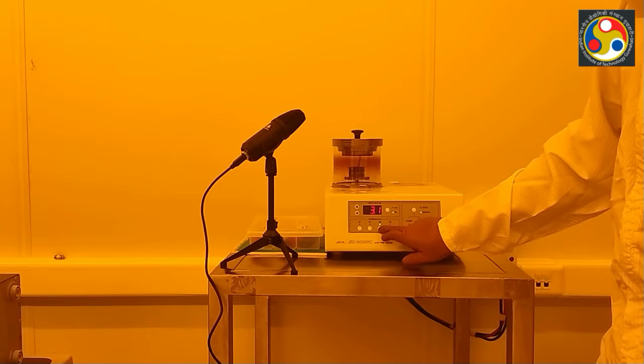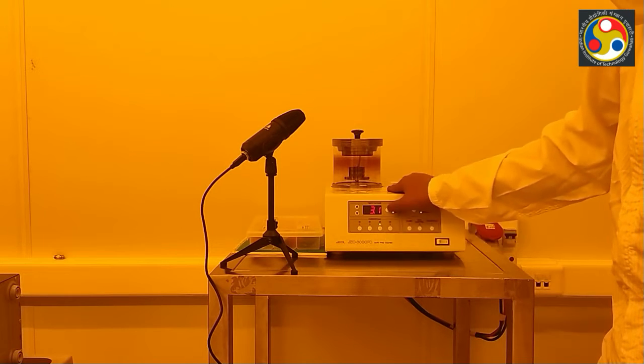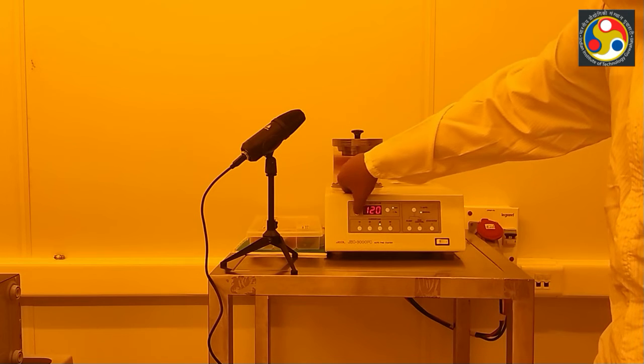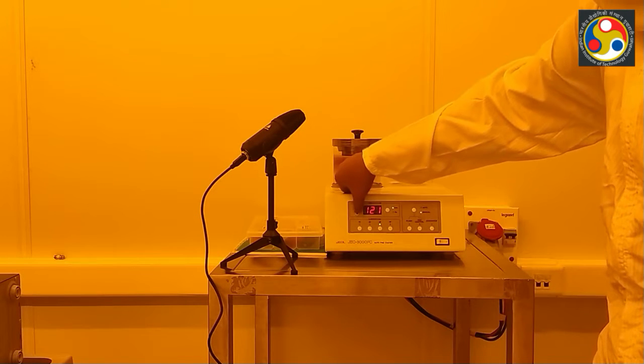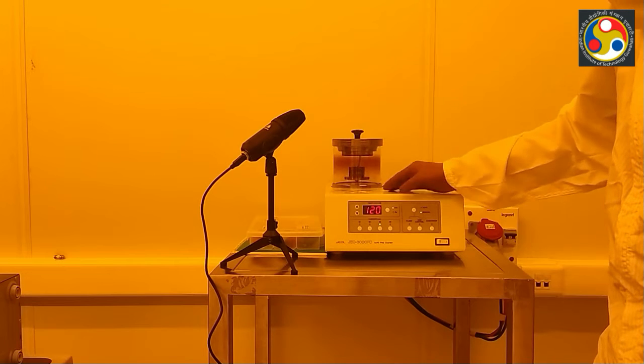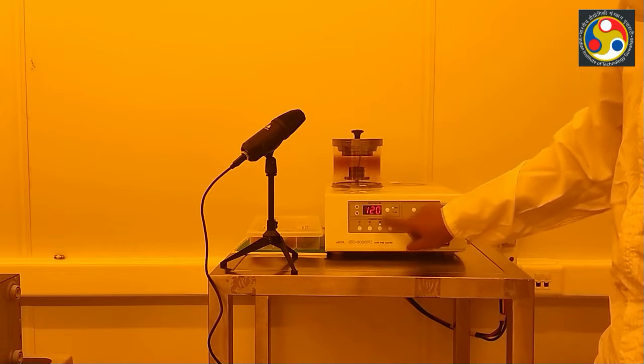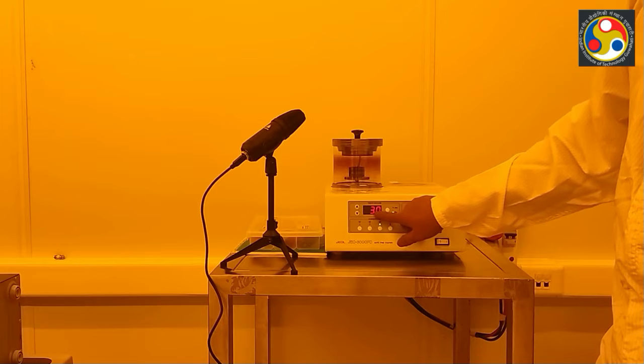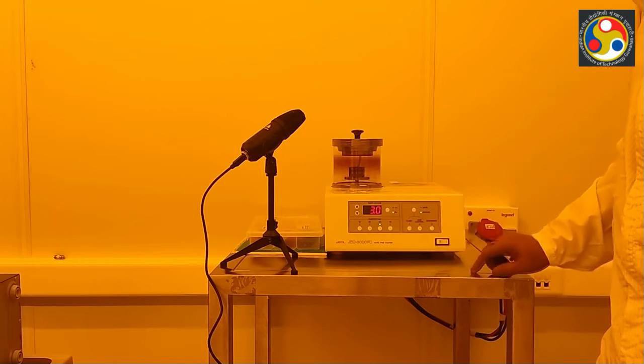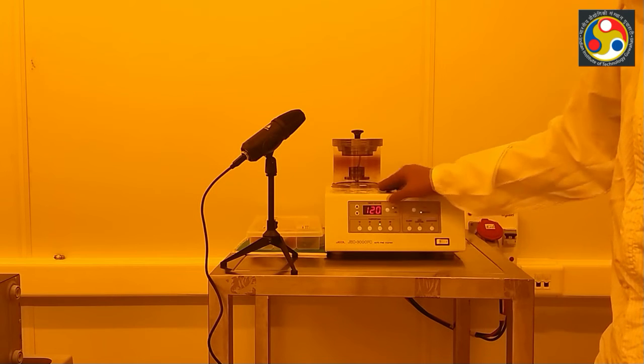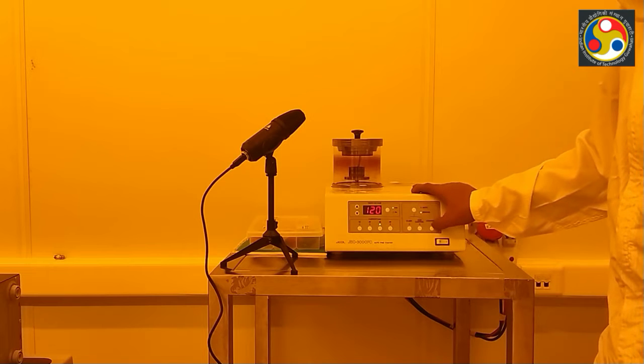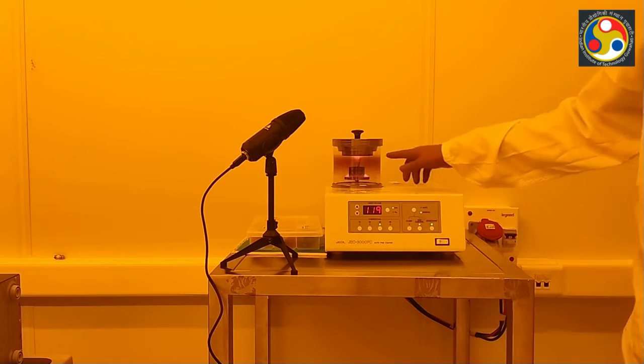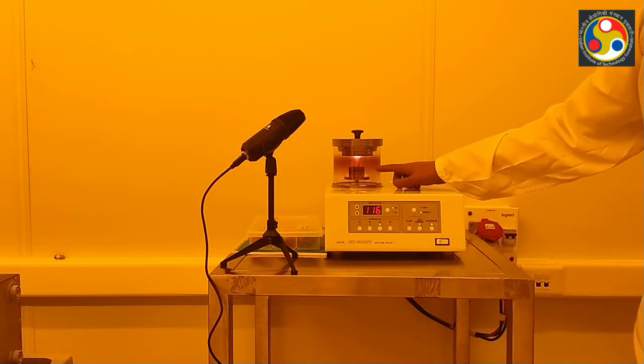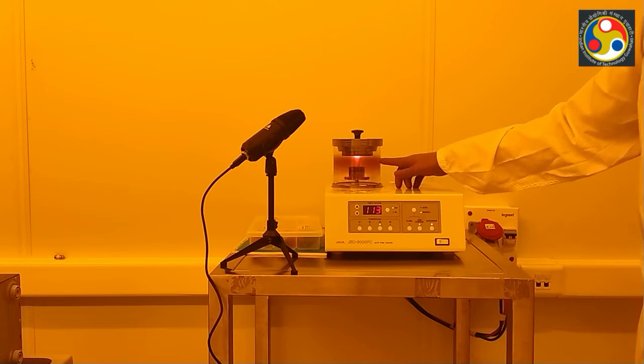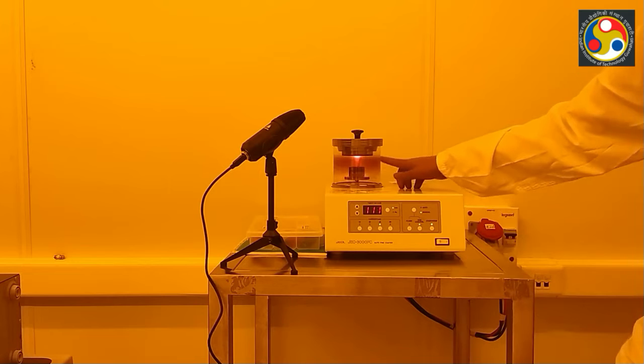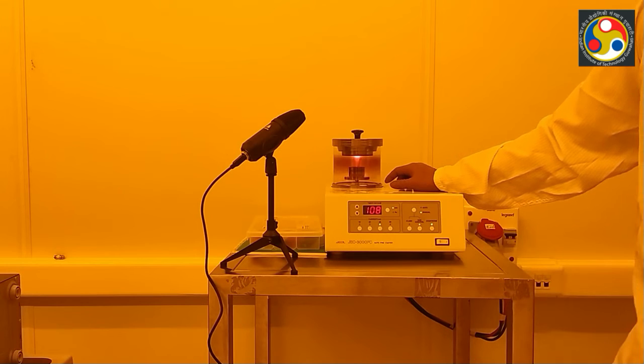The current I am going to use is 30 milliampere and the time I am using is 120 seconds. I can change this time value. I am keeping it 120 seconds and 30 milliampere current. And now the pressure is 3 Pascal, so I can start the system. Time is 120, 30 milliampere current. I am starting. Now you can see inside the vacuum chamber there is a pink color coming. This color is a manifestation of a plasma.